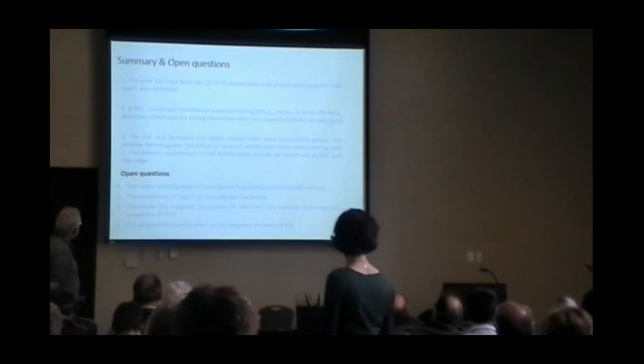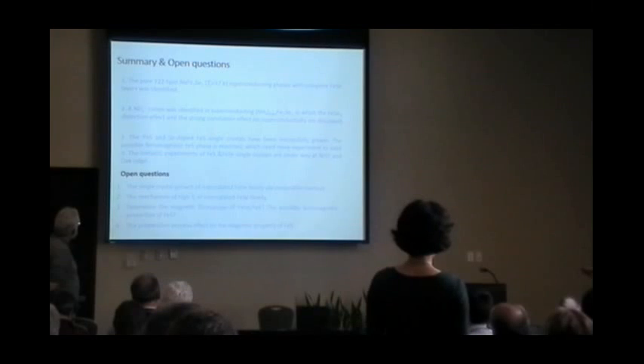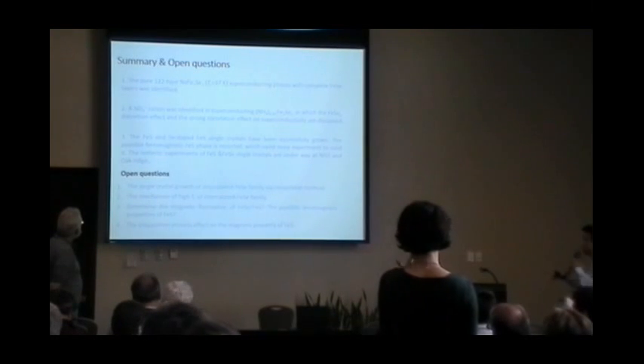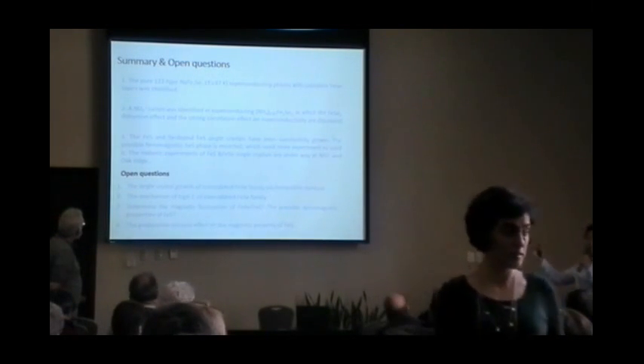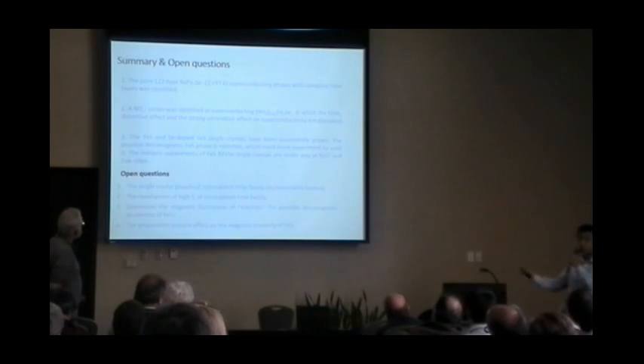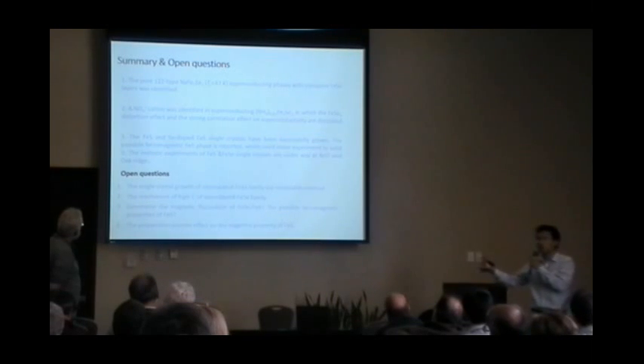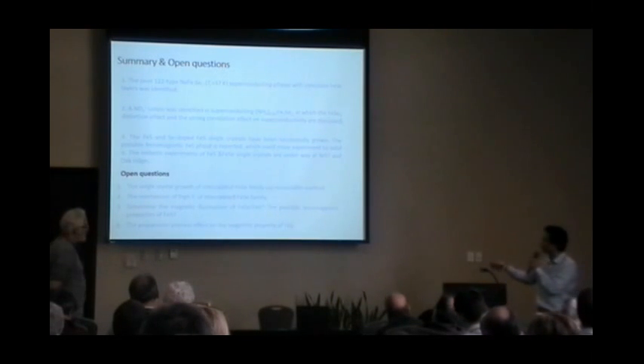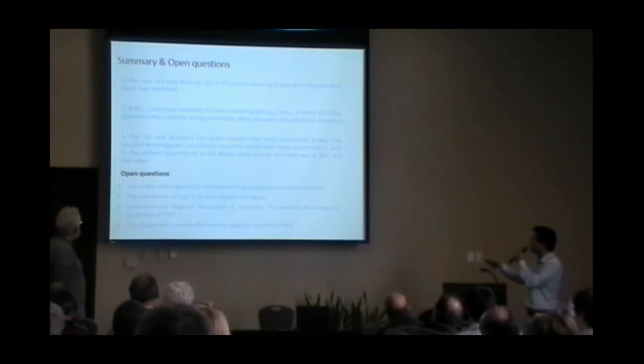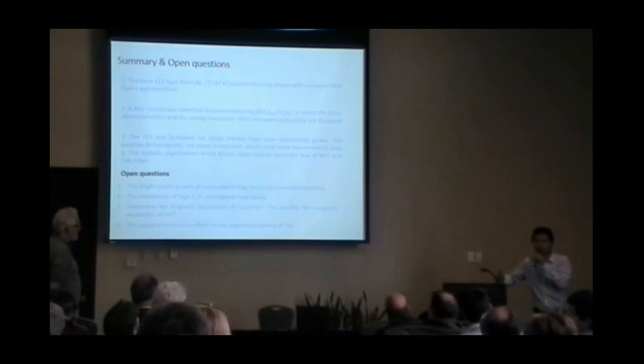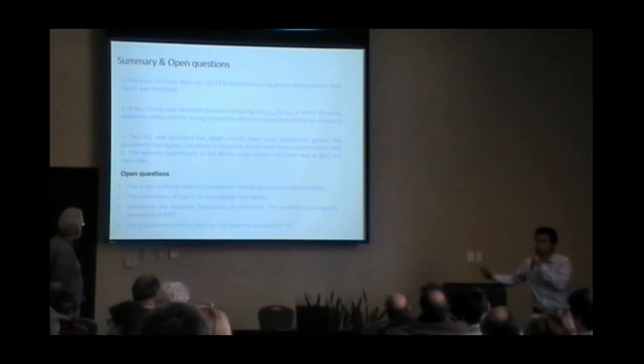So basically there are two questions. Why is the TC of the intercalation sample so high? The bulk 1-1 sample is around 8 K. But when you intercalate some molecules between the layers here, TC is around 40 or 50 K. But about this series of samples, we only got the powder sample. We don't have the single crystal sample, so we cannot know why the TC is so high.